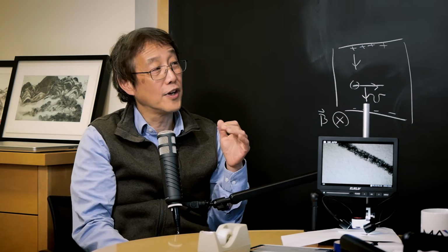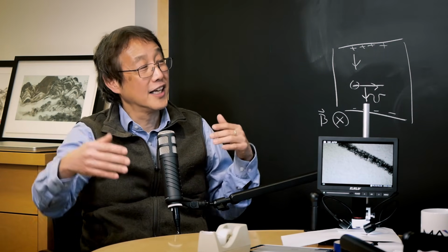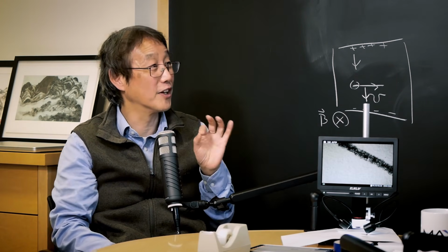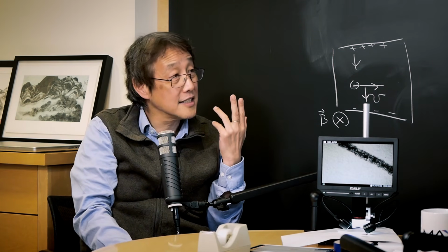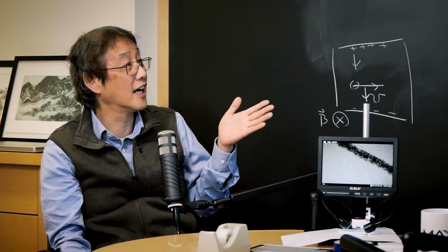So can you do the quantum Hall effect measurements? Not yet. Shubnikov oscillation is a precursor of the quantum Hall, right? To get into quantum Hall, you have to get to a really long period of Shubnikov oscillations. In other words, you have to populate only a few Landau levels, and that's where you get reliable quantum Hall, right? So we still have some way to go. Part of the reason is it's not graphene, it's graphite. The thinnest crystal we could get is probably 3 to 5 nanometers, which means something in the range of 10 layers, right?